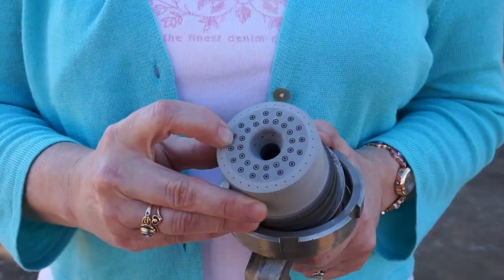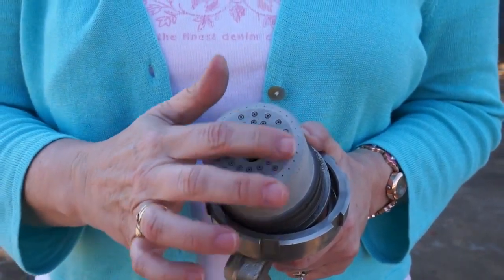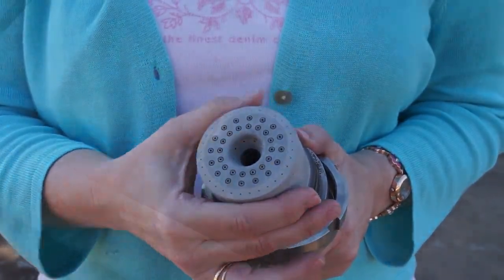The traditional technique actually uses a lot of intensive machining — there are a lot of different parts to machine. For our new injectors, we actually bypassed all the machining, welding, and brazing, and made these new pieces in one piece with selective laser melting, which is a 3D printing process. We fabricated these in-house in one piece, getting rid of all 32 braze joints and all five welds.